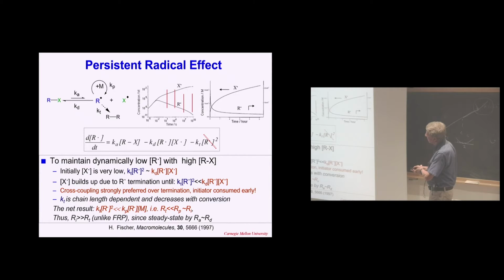And this rate constant of cross-termination is practically also diffusion controlled. If it would be slow, you would have a poor control. So you would like to have it as fast as possible, but only with this carbon-based propagating radical, not with itself.